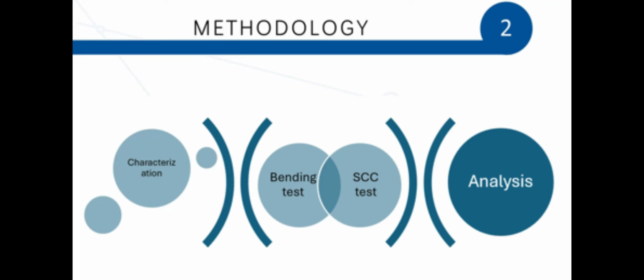And how did we do this study of this phenomenon? Well, the experimental methodology first involved performing metallurgical and mechanical characterization of each one of the steels used, which met the specifications described for API 5L X56 and X60 respectively. Once the test steels were evaluated, they were subjected to an SCC testing model for 6 months, as described in the NACE TM0177 standard, which also describes the 3-point bending method for specimens.